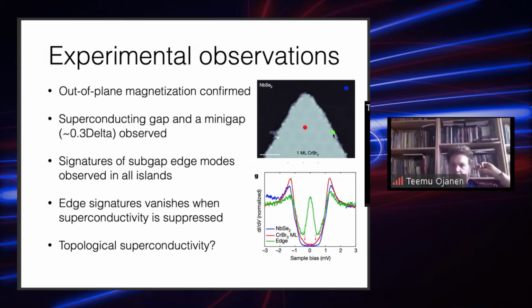And of course, interestingly, when they are measuring the dI/dV at the edge of the magnetic island, so at the edge of the sample, which would be your tentative topological superconductor, they see this type of feature. So they see that inside this mini gap that they see in the bulk, there is strongly enhanced local density of states, which is peaking near the gap center.